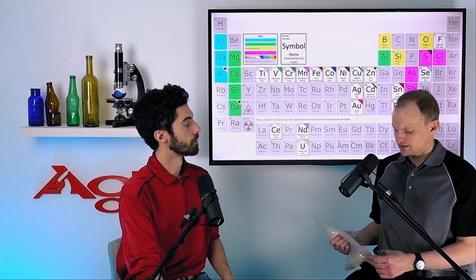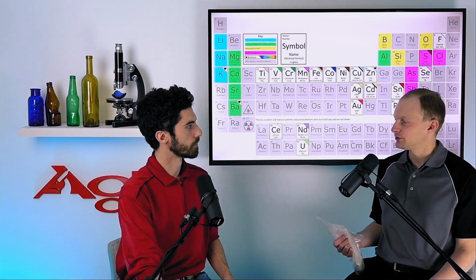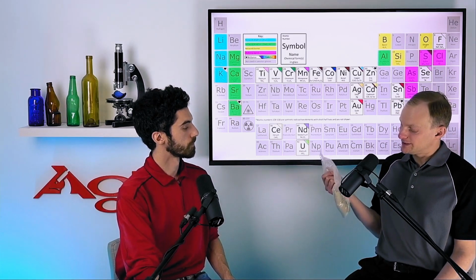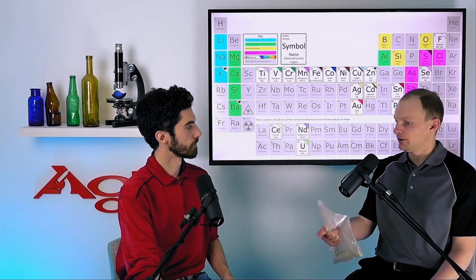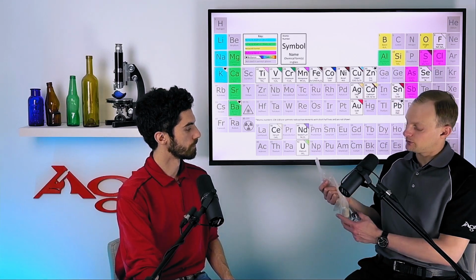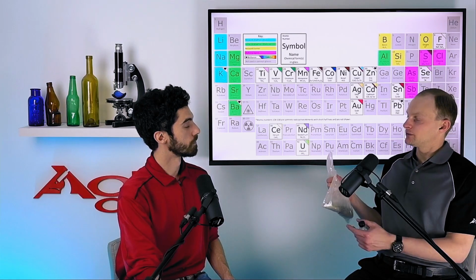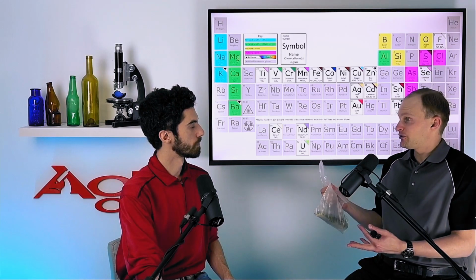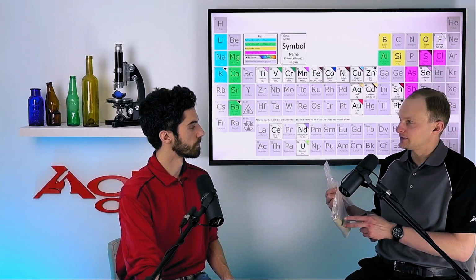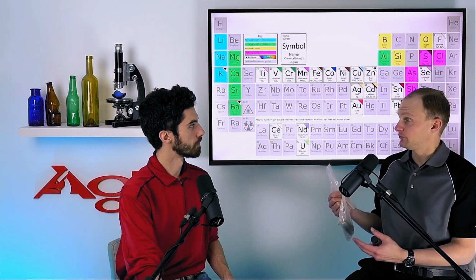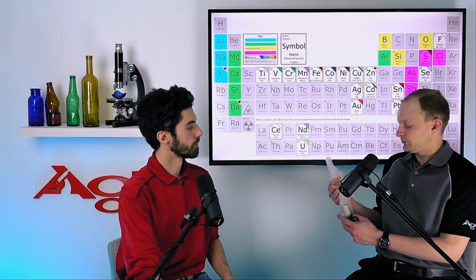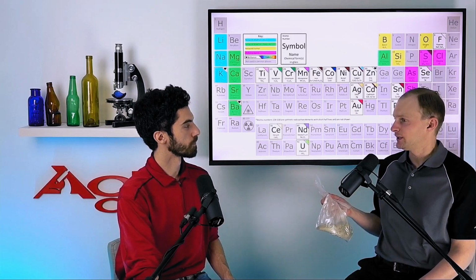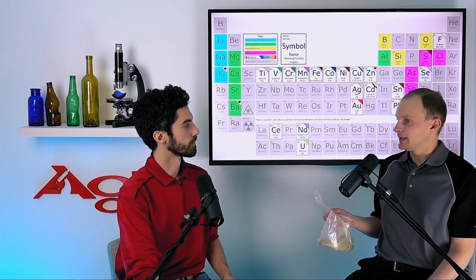I think for every 10% or so of cullet we use in the mix, we save a couple percent off of our energy. It takes less energy to melt cullet than it does to melt all these raw ingredients because all the chemical reactions have already happened. Glass can be melted back into any other shape you want, really, if we just provide enough temperature to get to where it can flow again. So we're really not losing anything, and we use this as our raw material to supply some portion of our batch.